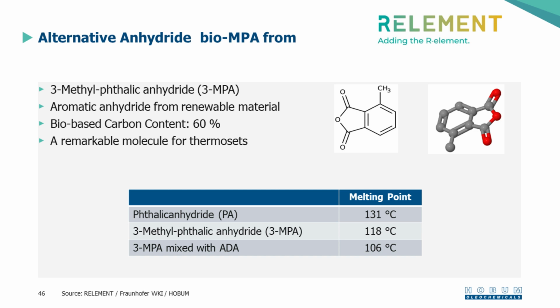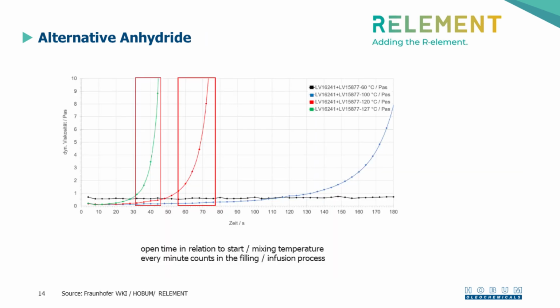Why is this important? If you look at the fill times that we have to fill the voids, either by infusion or resin transfer molding, it's a pretty speedy process at higher temperatures. So if you look at the green line, it's 127 degrees. You have about 30 seconds, and then the viscosity has already doubled. And you have to really hurry up to get material into the void or into the fabric. At 120 degrees, we are already at 1 minute. And at 100 degrees, that's the blue line, you have about 3 minutes, which should be sufficient to fill the entire void. So it's very important to lower the melting point in this respect. And that can be done with 3 MPA in a very nice way.